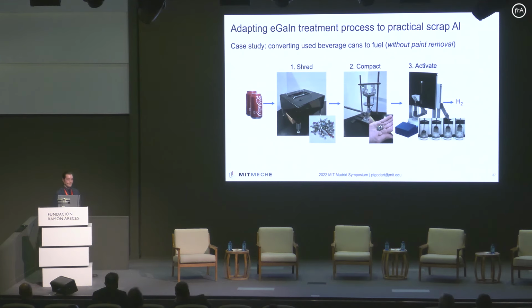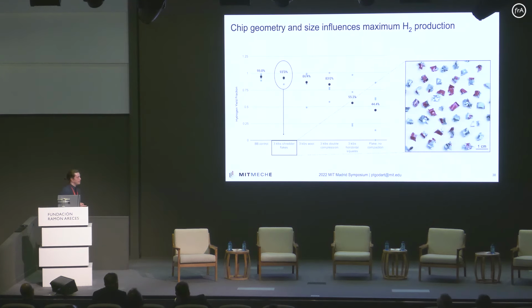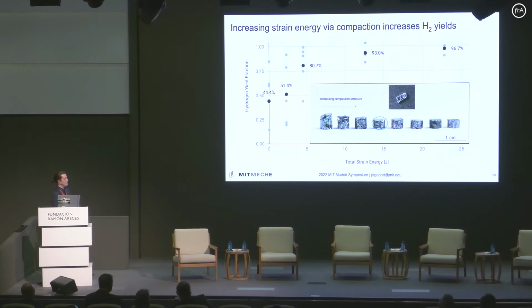And we developed this process for very simply just shredding the aluminum. This is actually a paper shredder that's been slightly modified. We compact these shreds into pellets and then do this surface treatment of the gallium and indium. We showed that there are a number of interesting parameters that affect the reactivity of these scrap pellets, including the geometry of the chips that go into the pellets, and also importantly, the total strain energy and compaction pressure used to make those pellets.